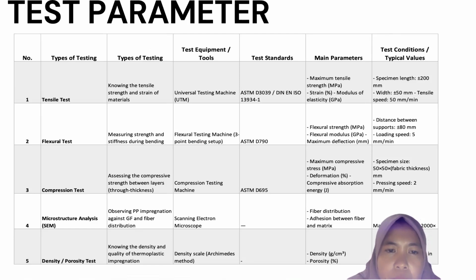Parameters: flexural strength, flexural modulus, maximum deflection. Loading speed 5 millimeter per minute. Three, compression test: testing the compressive strength between layers, strength and thickness. Test standard ASTM D695, parameters: maximum compressive stress, deformation, compression absorbed energy. Sample 50, fabric thickness in millimeters, speed 2 millimeter per minute.